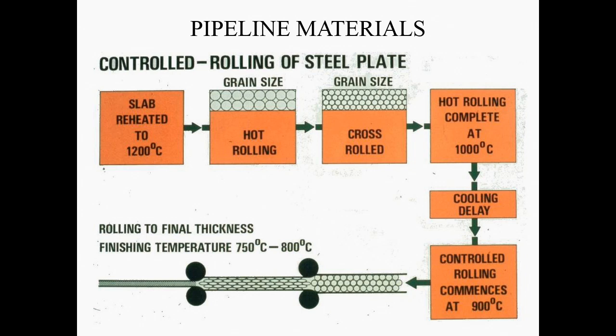Hot rolling reduces the grain size. If you put mechanical damage into a material, it reduces the grain size. We get recrystallization events taking place. And we want to have a material with a small grain size because that's a good way of introducing increased toughness and increased strength. So it's rolled in one direction, and then you turn the plate through 90 degrees, and you roll it in the other direction, so that's cross-rolling. And again, we've got this reduction in grain size.